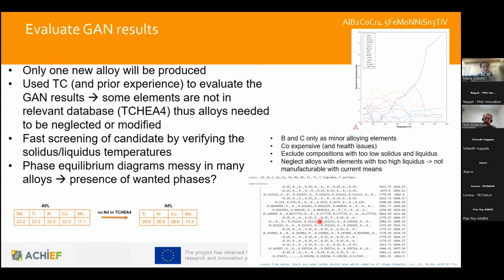And also after we did this fast screening, we computed the phase diagrams for these materials to see that there are some phases that are known to be beneficial for this. For many of these candidate alloys the phase diagram was really messy, so we decided to neglect those, so that we would be relatively confident that the final alloy would have the phases that are more usable for this kind of application. And also boron and carbon were decided so that if the alloy has any of those, they should only be a minor alloy element. And also cobalt was excluded, since it might cause some health issues.